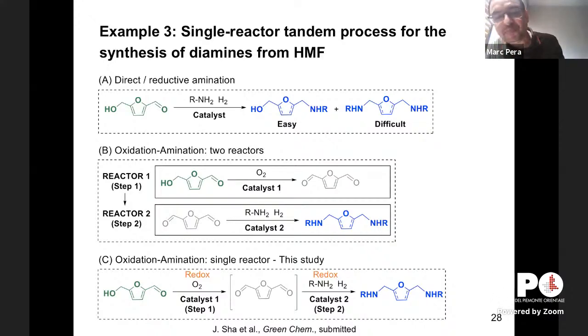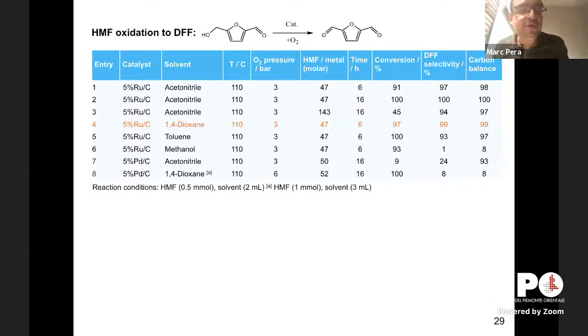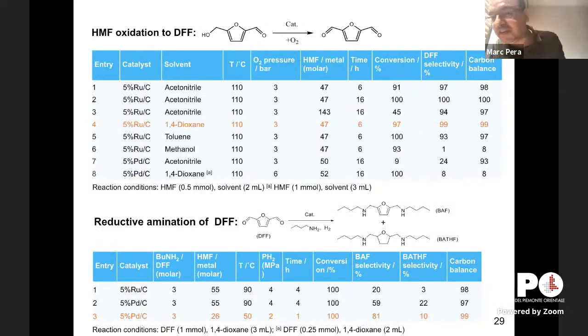This is the trick. Very briefly, I'm not going to enter into details. My student was very skilled. He found two catalysts that are not antagonistic. One catalyst that works well for the first step is ruthenium on carbon working in dioxane. It's very important in this process that since we're going to work in the same one-pot process, we need the same solvent for the two steps. So we tried also dioxane for the second step, and the good catalyst that is working is palladium on carbon. So we can run the two steps separately with the same solvent, one working well for the oxidation of HMF to DFF, and the second from DFF to the different amines.